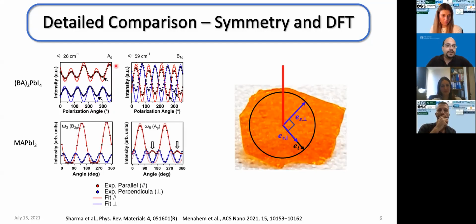And you can see here for the 2D perovskites, you have an AG and a B1G mode. And for the methylammonium lead iodide, we have a B2G mode and an AG mode, which now allows us to compare not only the frequencies of the modes, say whether they are in close proximity, but also their symmetries. And we found great correlation between the frequencies and the symmetries of the materials.